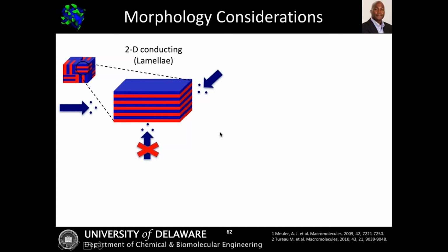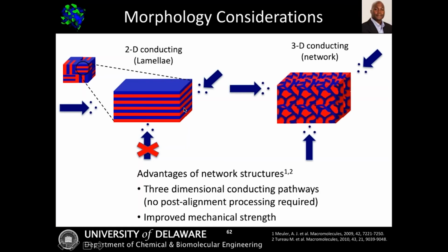In this particular example, I can have things like lamellar structures where I can get conductivity in, say, 2 dimensions if I'm looking at conducting the blue dots through the blue domains. But I can also start designing 3-dimensional networks, for example, where I have conductivity in all 3 dimensions. So what are some of the advantages of these network structures? First, I don't have to do any post-processing alignment for these materials. And so that's quite nice.